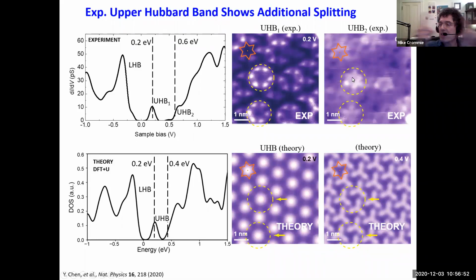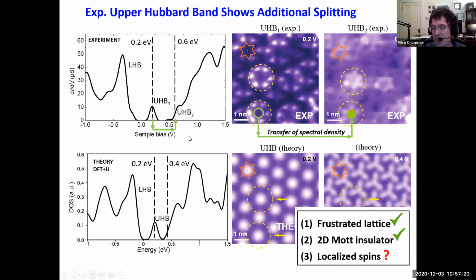That's exactly opposite behavior. And what we believe is going on is that there's an electron localized in the center of the Star of David. And so when we try to add another electron into the upper Hubbard band, the state density gets pushed to higher energy. That is not captured in the DFT, but that's what's happening experimentally. So basically the correlation effect is splitting the upper Hubbard band a little bit. And so the bottom line here is that we have a Mott insulator, but it's not a completely generic Mott insulator. We have this funky behavior where the upper Hubbard band splits a little bit.